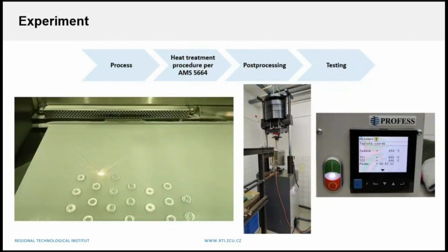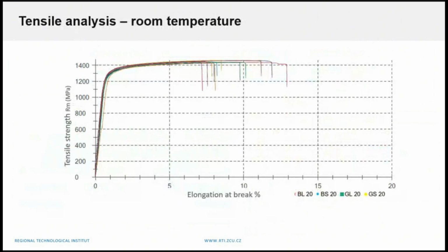So for the experiment, we use the standard process parameters in this case, because we want to show what could happen with the material if somebody bought the machine, started to print and used the standard process parameters without optimization. Heat treatment according to standard, and of course the testing.